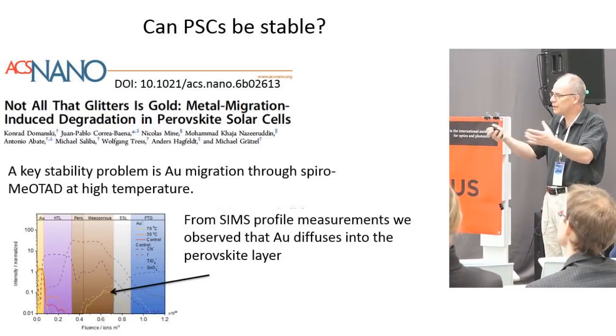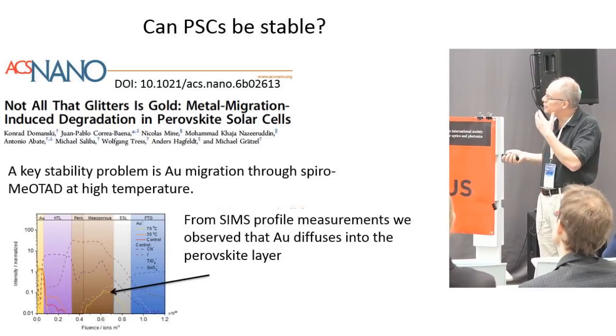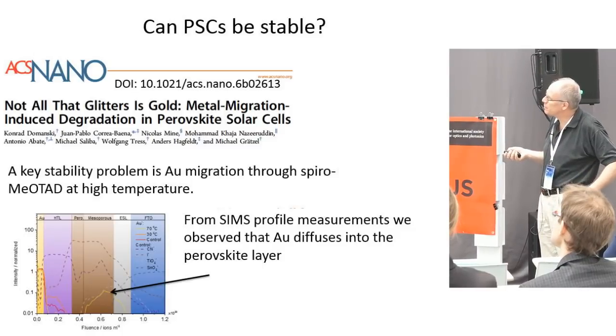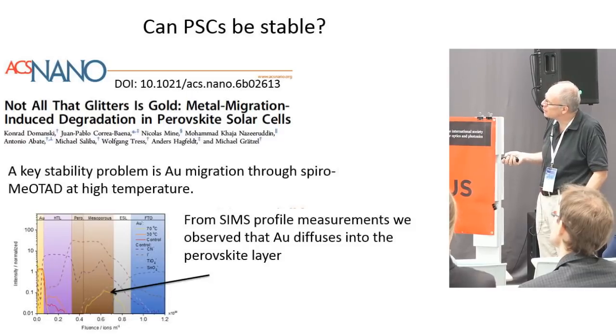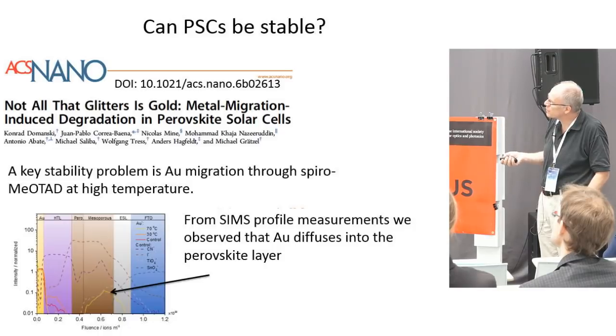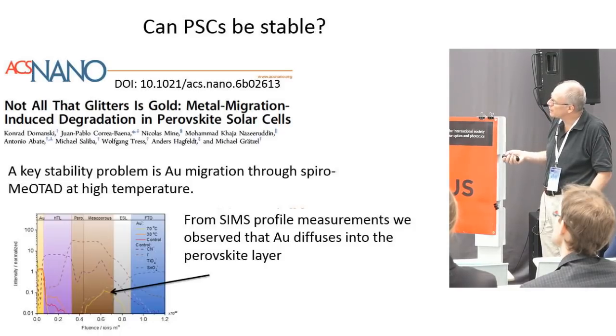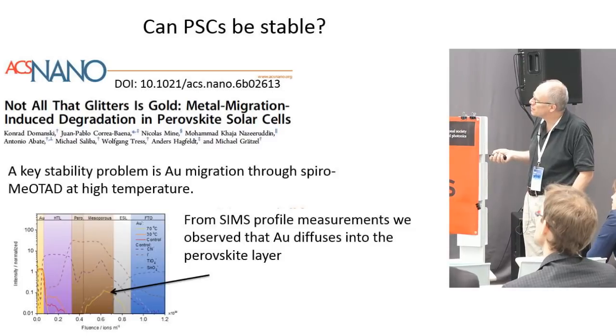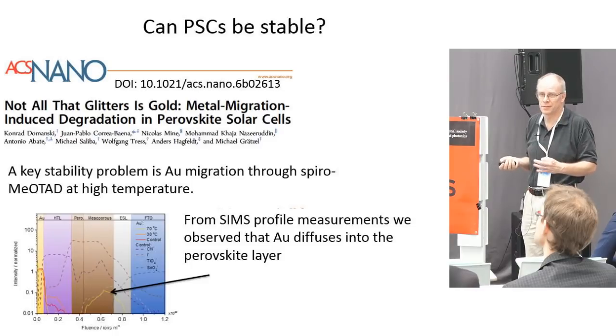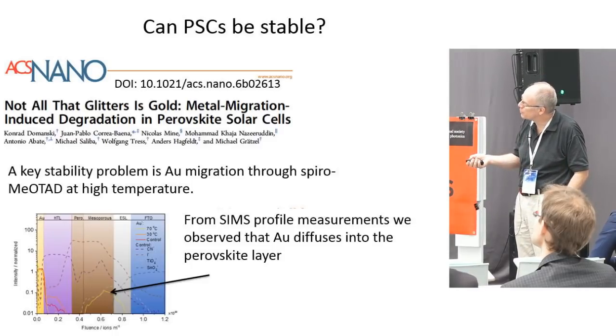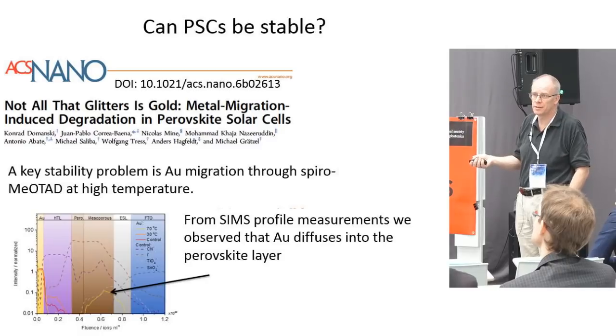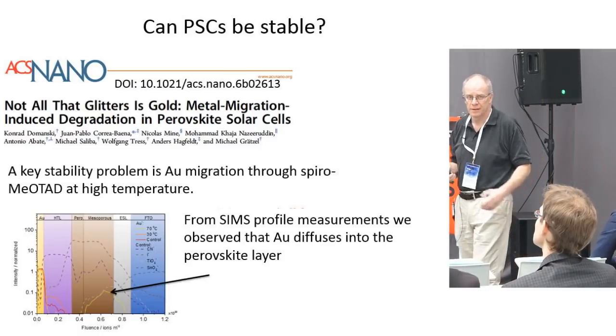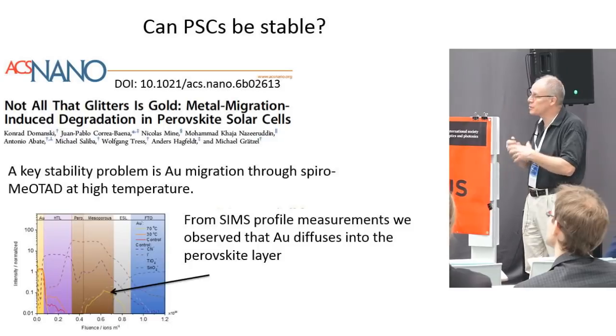And we thought, okay, now things are problematic. And the perovskite, the ions are moving. We made a SIMS profile. That means that we can look at the elements we have throughout the device. So here is the contact. We have the gold layer. We have the spiro. Then comes the perovskite layer, TiO2, and the conducting glass. And to our surprise, the problem of stability was not perovskite. It was the gold contact. So gold diffused through from gold even into the TiO2 layer. So gold is problematic.